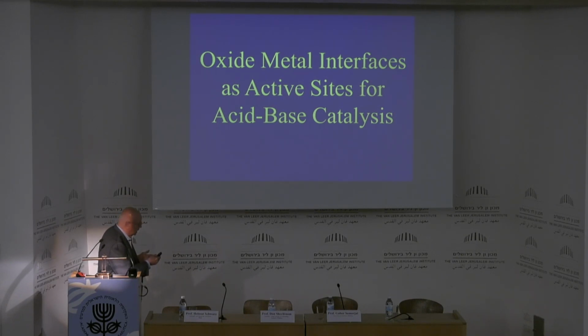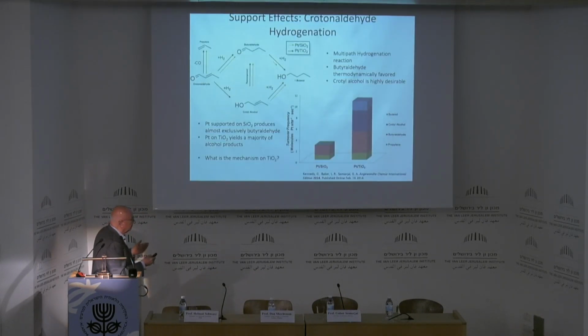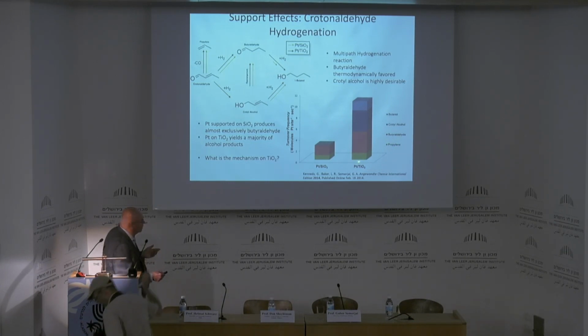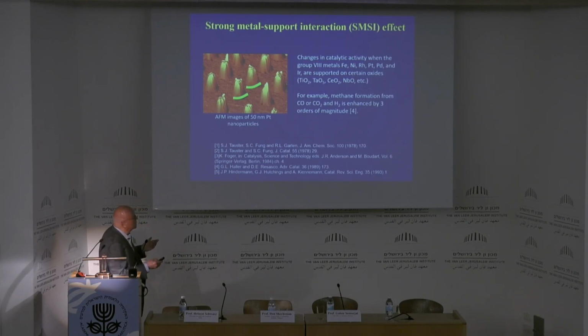But there is another type of catalysis, and this is what we call acid-base catalysis, and this one is interestingly dependent on the oxide support. If you look at the oxide support for a reaction like crotonaldehyde, two double bonds forming this molecule, if you put it on silica as a support, you make very little, and these are the compositions. If you put in a support of titanium oxide, you get much higher turnover rate and very different compositions. So the oxide-metal interface does what we call acid-base catalysis. And this was the discovery of hot electron flow between the oxide and the metal, and this at the oxide-metal interface is where the chemistry occurs.